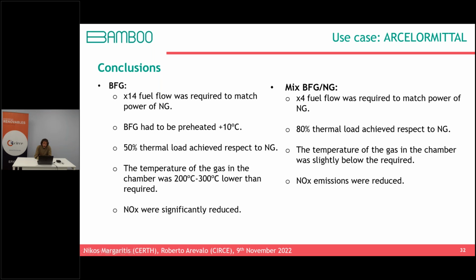Regarding thermal load, so heat transfer to the load, okay, with BFG only 50% of the thermal load was achieved, but using a mix we reach 80%, and the rest 20% can be tuned, of course. This could be done, for example, with simulation to come up with the right value of the mix that would give us the 100% load.